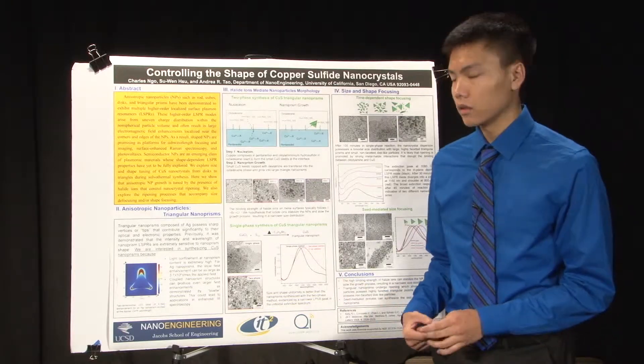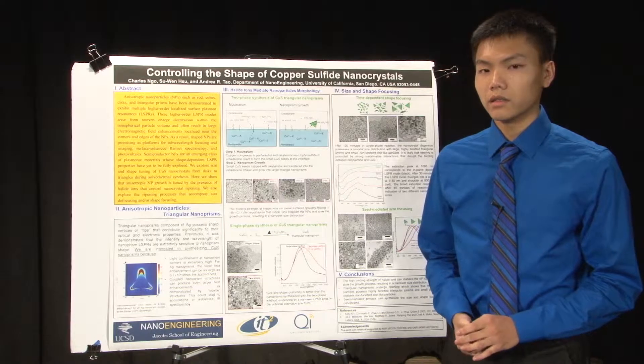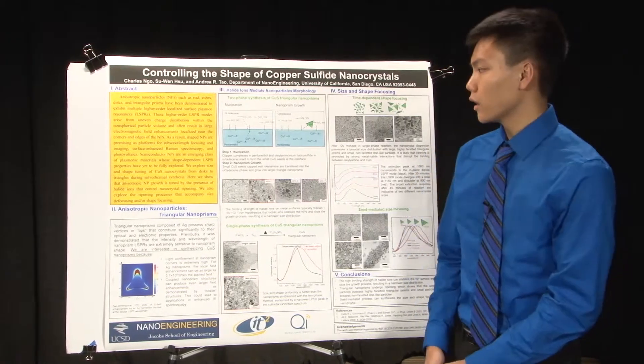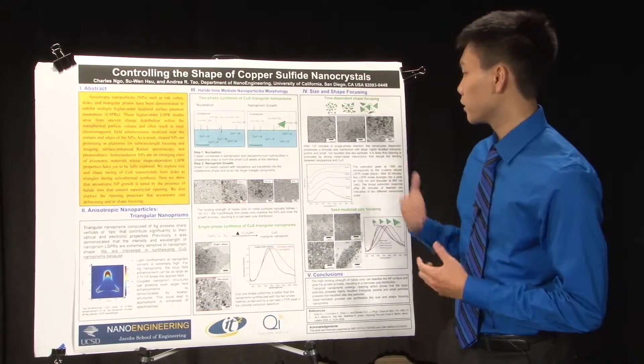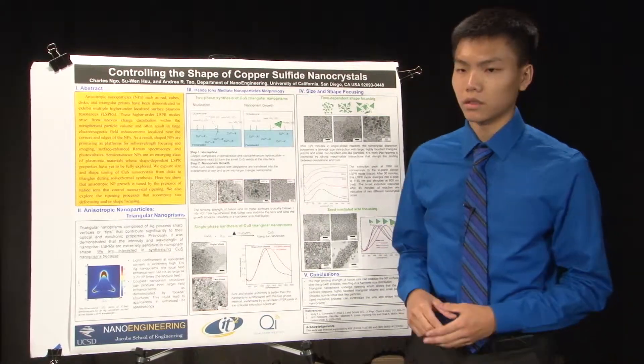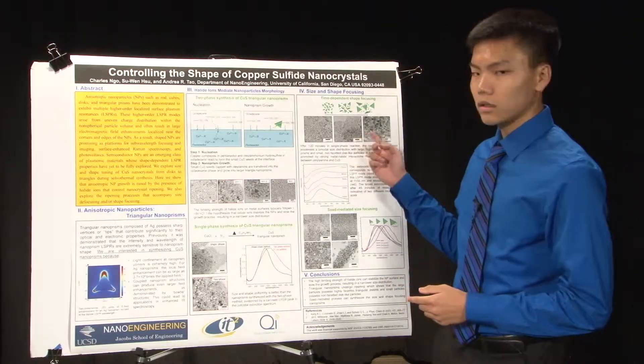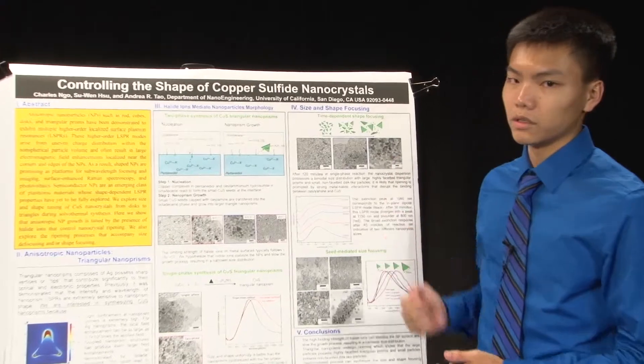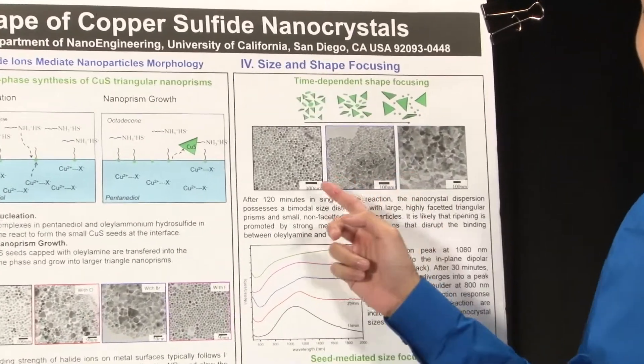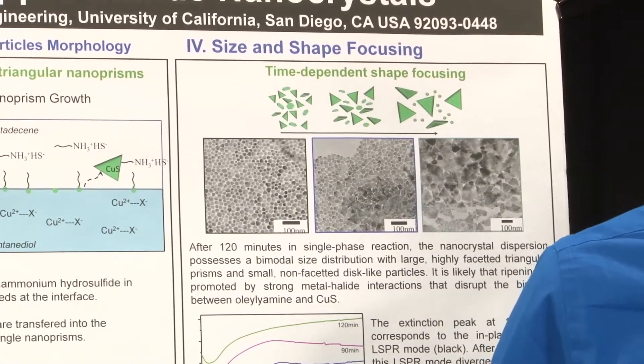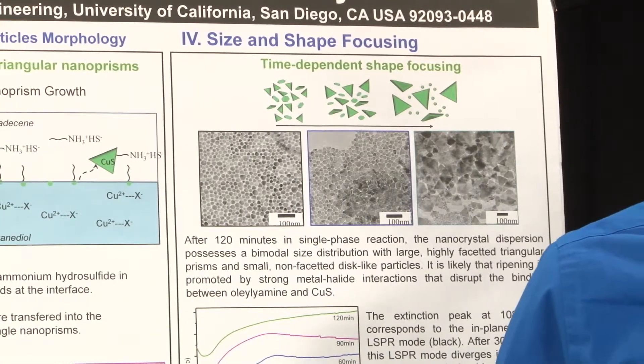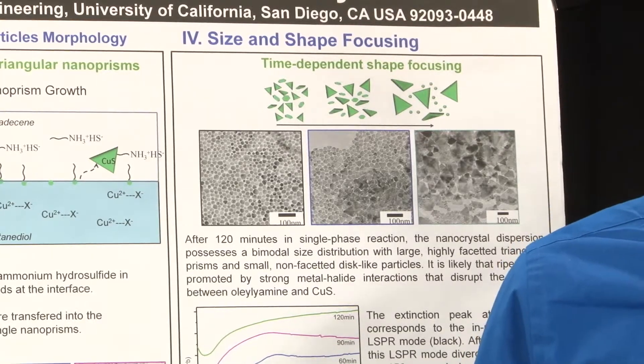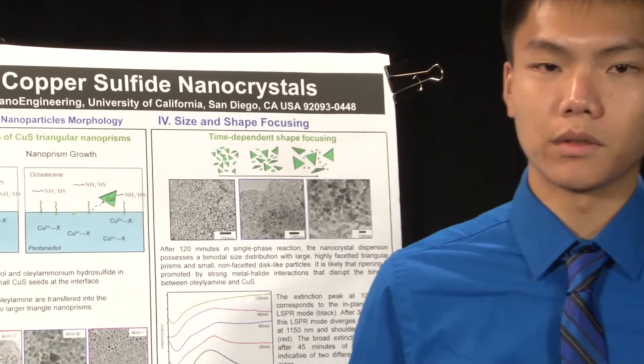The next step was to look into size and shape control. What we noticed is that when you leave the reaction to go on for a longer time, you get larger nanocrystals or nanoprisms, probably due to the introduction of halide ions. But a longer reaction time doesn't always yield completely similar particles. What you see here is a ripening effect, where prisms with halide ions are growing while the disk particles without halide ions are shrinking.